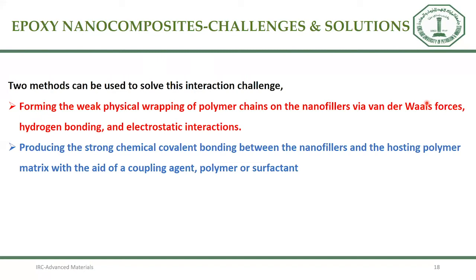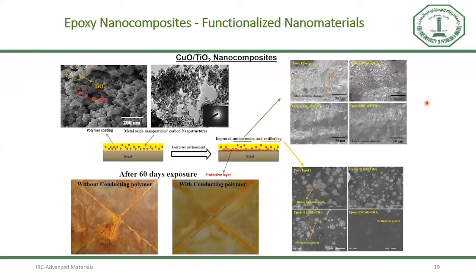the weak physical wrapping of polymeric chains on nanofillers through van der Waals forces, hydrogen bonding or electrostatic interaction, as well as producing strong chemical covalent bonding between the nanofillers and the hosting polymer matrix with the use of a coupling agent, polymer or surfactant. Herein we developed two nanocomposites based on copper oxide and TiO2 to improve the anti-corrosion as well as anti-fouling performance of the epoxy coatings.